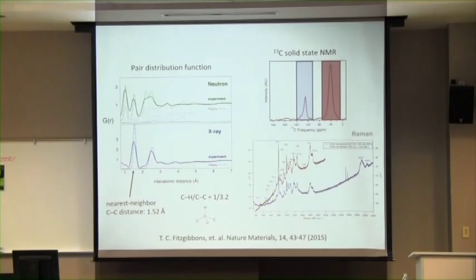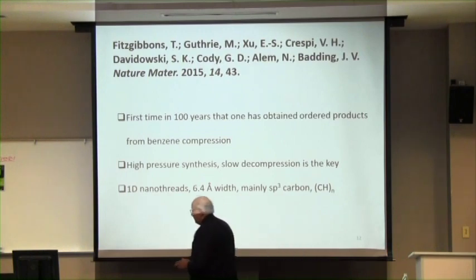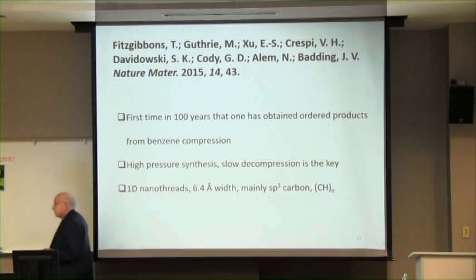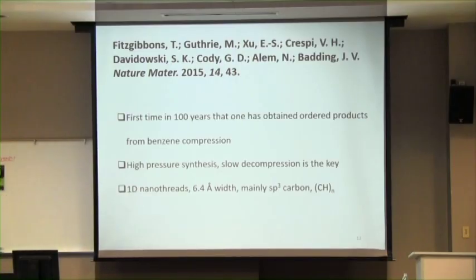And the most informative actually is Raman on this. And those Raman structures are very characteristic of saturated individual hydrocarbons which have CH groups on them and which have 6-membered rings. So here is the achievement of the Penn State group. For the first time in 100 years, there is something somewhat ordered coming out from the compression of benzene. And the slow decompression is the key. There are one-dimensional nanothreads about 6.4 angstroms wide, and they're mainly sp3 carbon.